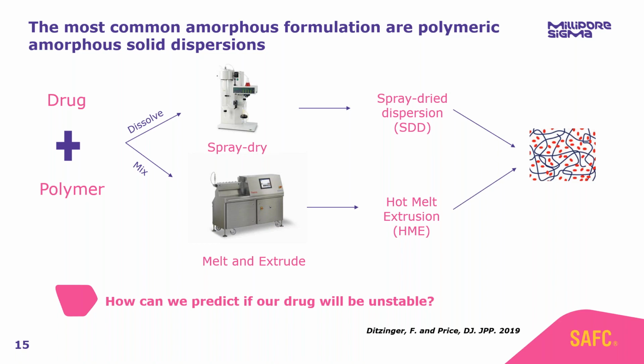In a solid solution, the drug and the polymer are homogeneously distributed. That means you have a perfect mixture of that drug in that polymer, and as a result, a solid solution is formed. The solid solution is the ideal scenario for a polymeric amorphous solid dispersion, because if you ensure that your drug is fully homogeneously combined, then you have a bigger stabilization effect of the polymer on that amorphous API.